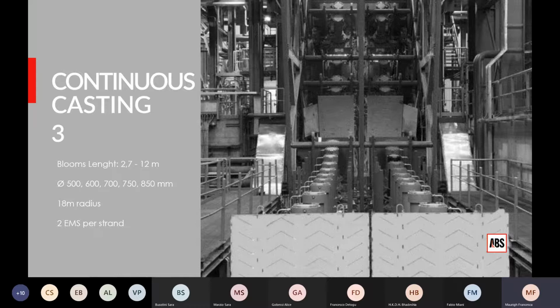And what is interesting is that we can cast almost any kind of the grades that are produced in ABS. So we could cast high carbon grades, we could cast high chromium grades. So we could adapt this machine to cast also critical grades from the side of solidification with good performances in terms of core soundness.